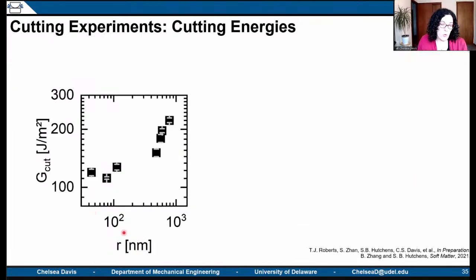Others have already reported the relationship of how sharp a blade is to the energy required to cut, but we did want to make sure that we were reproducing those experiments. So if you plot as a function of blade radius, or how sharp the blade is, there does seem to be a threshold below which there is no relationship between the sharpness of your razor blade and the cutting energy.